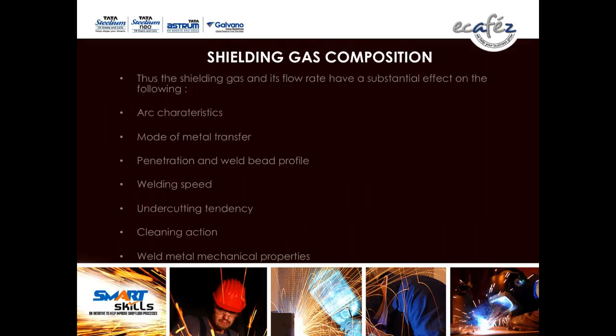Stabilizes the arc root on the material surface. Ensures the smooth transfer of the molten metal droplets from the tip of the weld wire. Shielding gas composition and its flow rate have a substantial effect on the following: arc characteristics, very important; mode of metal transfer in the MIG process, very important.